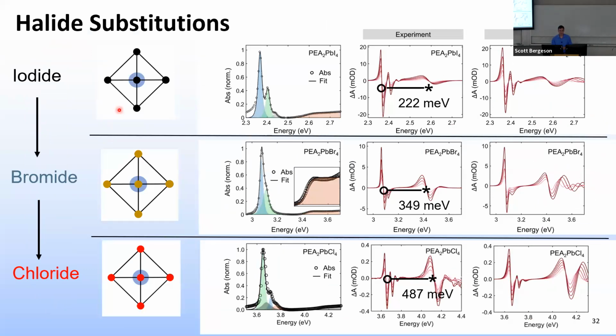And being able to make these measurements allows us to do things like see what happens when you substitute different halide atoms. So change it from iodide to bromide to chloride, for example. If you look at right here, this is that Franz-Keldysh feature. We can measure the band gap here and here and here. And we can then measure the binding energy as being the difference between this excitonic absorption and where the band gap is. And this basically had not been done before, at least not with any degree of precision.